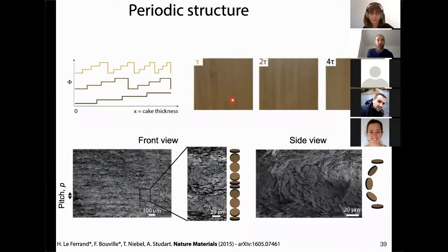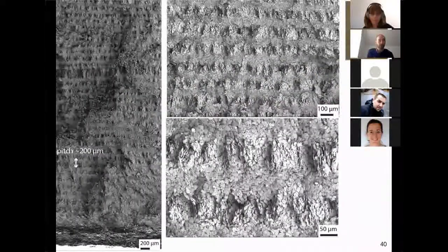And this is just an optical microscope. So you can see the bands here that are just coming from the different orientation of our platelets in the sample. And if you look at the microstructure in the SEM, we have what we call the wave microstructure. So you have platelets that go like this inside your sample, then like this. And each layer, you can program each layer's orientation the way you want. And eventually we managed also to change the setup and make a proper Bouligand structure.